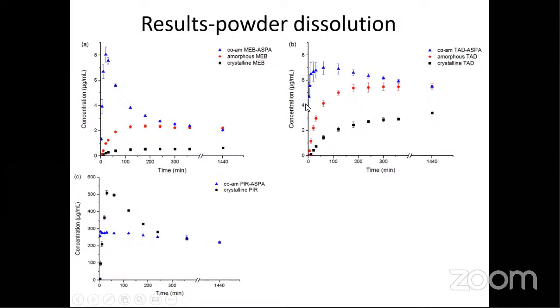We can see here the co-amorphous dissolves much faster. And in the case of piroxicam, because there is no amorphous piroxicam, there are only 2 samples. The piroxicam crystalline black dots start here, dissolved a little bit fast, but also recrystallized. For the co-amorphous sample, it dissolved much faster, because at the beginning, within 1 or 2 minutes, the concentration is already very high. This means it dissolved very, very fast and always maintained this concentration. So basically, this also shows co-amorphous dissolved much faster than the crystalline one.